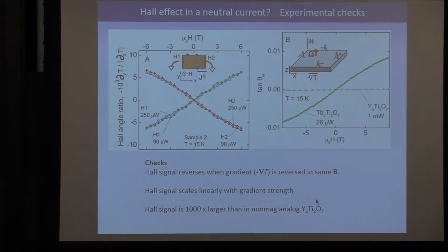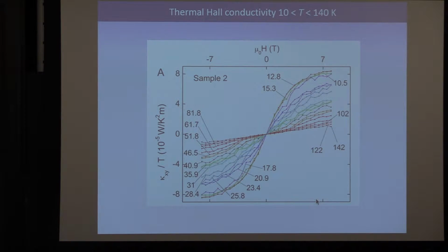So this is an intrinsic signal. It's an insulator that has spin excitations. They carry neutral current, and you can make their Hall current go to the left or to the right by either changing the current direction or the field direction. So it's a true Hall effect. So knowing that, then Max measured this in great detail. Here are raw traces of kappa XY, again divided by T. And at very high temperatures, it's still there. So it's not an abrupt appearance at some order. It's always there when you have spin excitations.